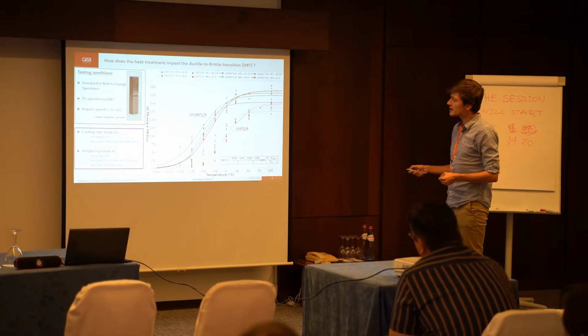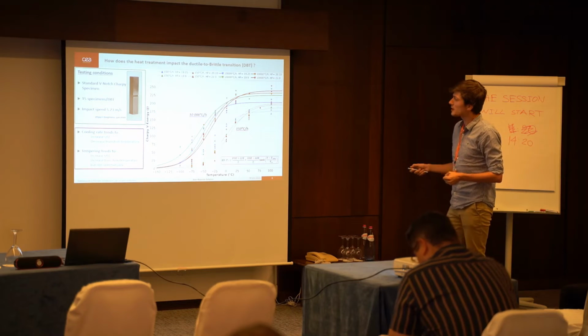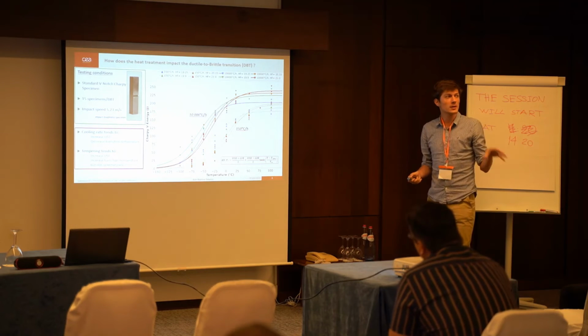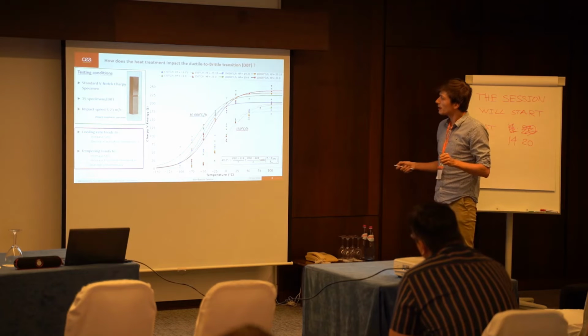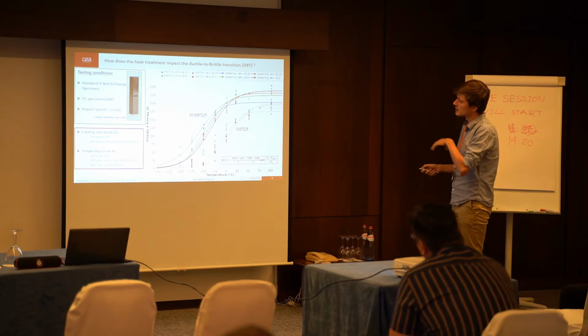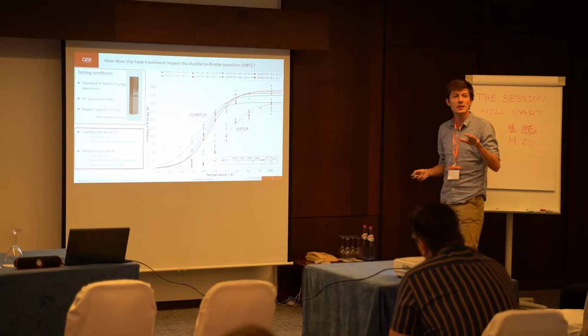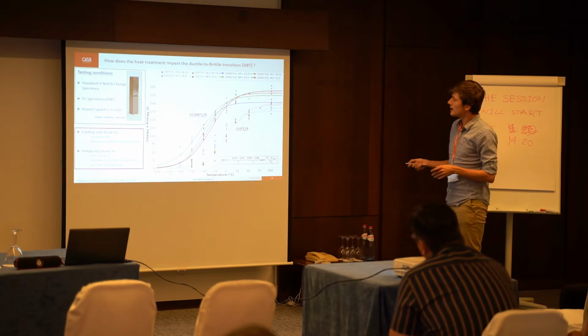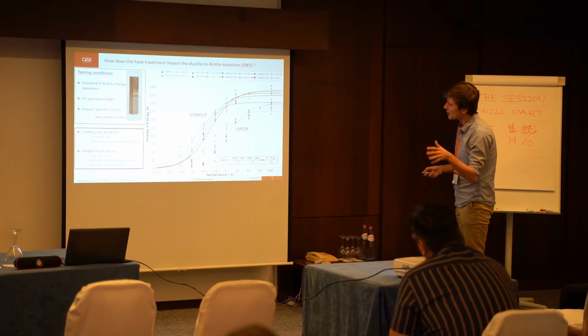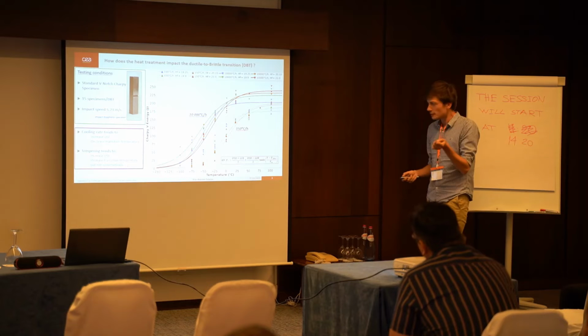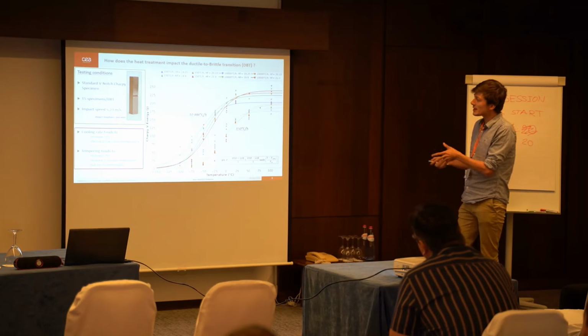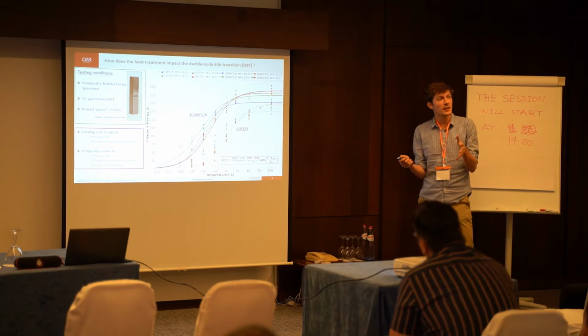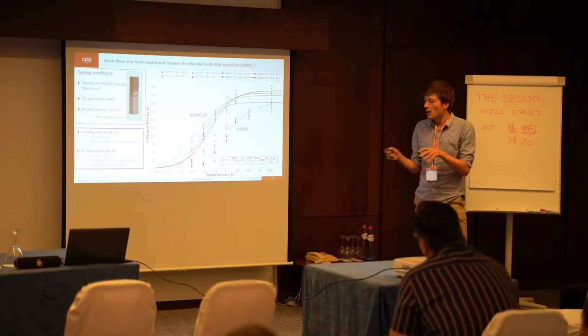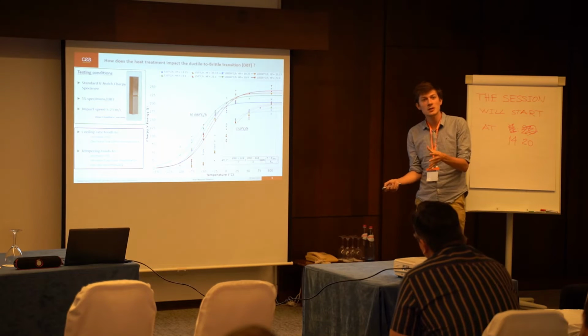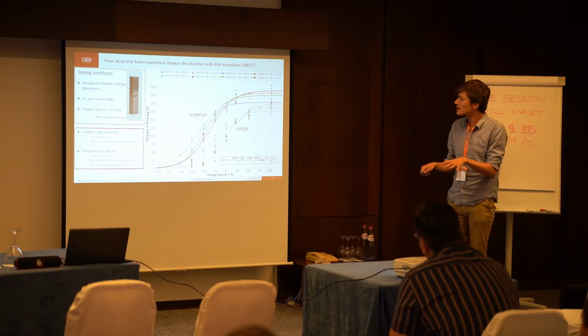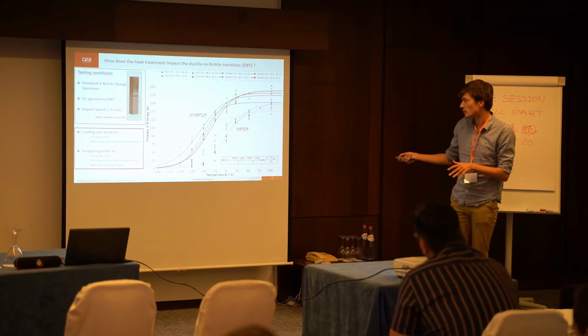Indeed, the fast cooled materials are much tougher than the slow cooled ones, with a transition temperature which is approximately 70 degrees lower, and upper shelf energy which is about 70 joules higher. And we see that tempering has an effect on the ductile to brittle transitions, but it's much less significant than the cooling rate.